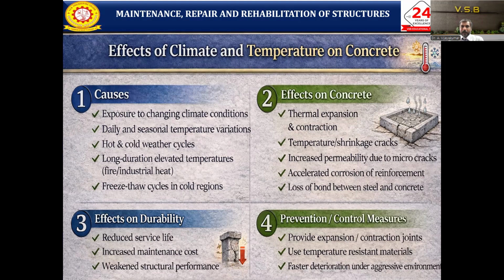So what will happen in the concrete member? Definitely for these reasons thermal expansion and contraction will happen, and failure may happen in the concrete structure. As temperature increases and decreases, shrinkage cracks will occur. Then permeability increases due to micro cracks. Essentially cracks will form as micro cracks. Then moisture will enter and the cracks will keep increasing, and permeability increases too. Then accelerated corrosion of the reinforcement occurs, so the rebar will corrode. And then definitely the bond between the steel and concrete is lost.